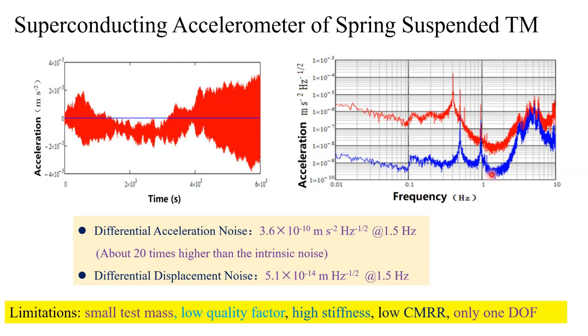The reason is that this test mass is very small, and a small test mass will give you higher noise. And the quality factor is low, only 10 to 20 thousand. A lower quality factor means the energy stored in the spring becomes heat very fast, and the power is high, so it gives you a lot of thermal noise. The high stiffness: as we remember, the test mass frequency is 13 hertz, it's very stiff and very difficult to push. And there is a low common mode rejection ratio, because geometry errors make the common mode rejection ratio not so good. Another thing is the test mass was spring suspended, so it only has 1 degree of freedom. It can only move freely along one direction. So we want to improve this.